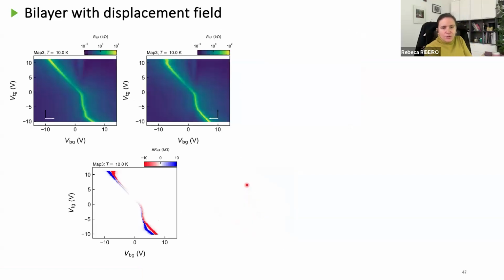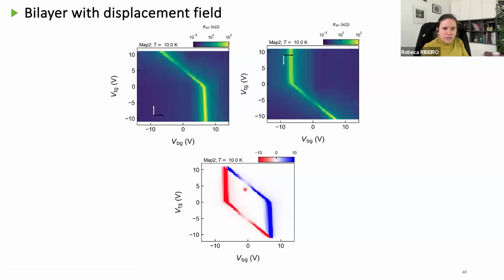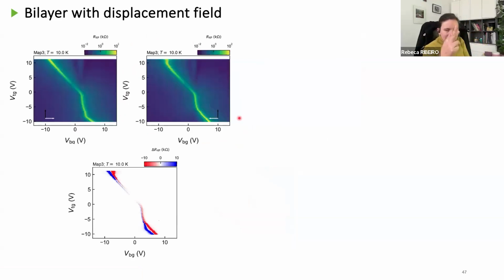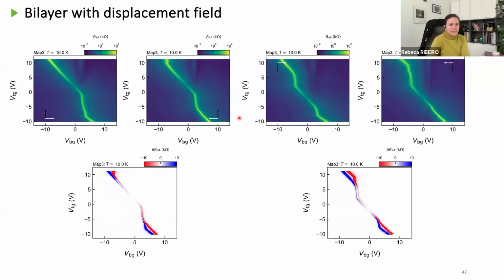So this also happens if you use, sorry, I didn't give you the details, but here we're using the top gate as a fast axis and the bottom gate as a slow axis. If we change the axis, the slow and fast axis, you can see that we do not recover that behavior anymore. However, if we go down with the same gate, we recover the hysteresis, because this one and this one do not follow the same path.